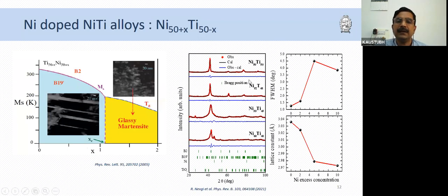We prepared these alloys, nickel 50, titanium 50, nickel 52, titanium 48, and so on. And we looked at their structure. The structure of stoichiometric alloy was essentially B2, and there was a small phase of B19 prime in this because the martensitic transition temperature is very close to room temperature. But when we look at the structure of the non-stoichiometric alloys, it is B2, but the width of the peak anomalously increases, and eventually another impurity phase emerges, which was identified to be face-centered cubic nickel metal phase.